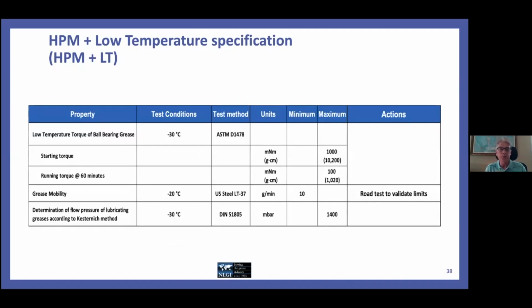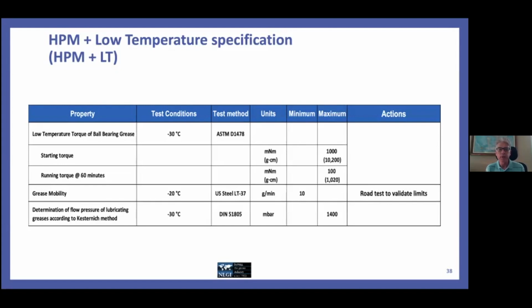So we added LT, and this one, we've got a number of tests. None of these are in GCLB. We've got the low temperature torque test again, D1478, but instead of -20C, we have -30C with the same limits as we have at -20C for the HPM spec. The grease mobility test has been added. This is the US Steel method. We've got that specified at -20C with a minimum of 10 grams per minute.